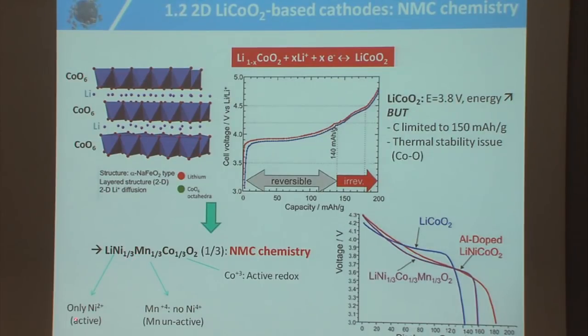And this nickel is nickel 2, meaning that it can be oxidized into nickel 3, nickel 4. This manganese is +4, not active at all. So it means that you replace a part of the cobalt with one inactive material, but with another active material which can be oxidized, so that in fact you don't lose a lot of capacity, but you have something which is, thermally speaking, much more stable.